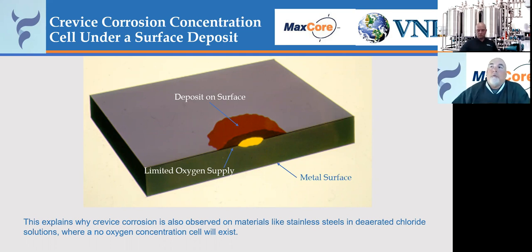And when that happens with this deposit on the surface, you're limiting the oxygen supply underneath here. And this becomes very corrosive because the concentration is increased underneath that deposit. So you can start to have a pit start to form at that location right there. So one of the things to keep in mind in showing this is that cleaning practices are very, very important when it comes to the integrity and stewardship of equipment. If you're not getting all your product off, then you can really have some issues when it comes to corrosion, just this under-crevice corrosion.